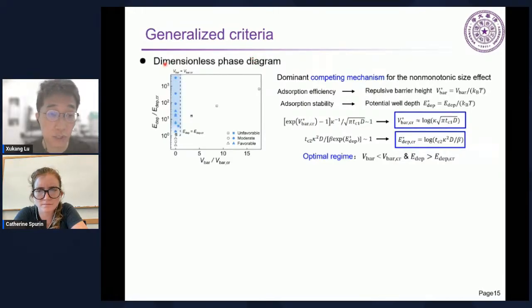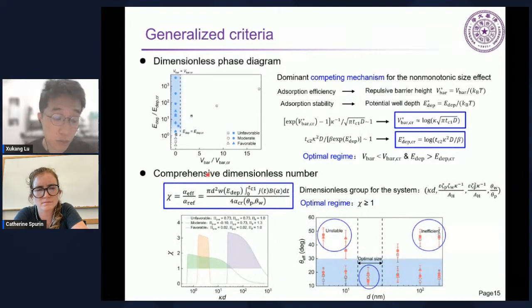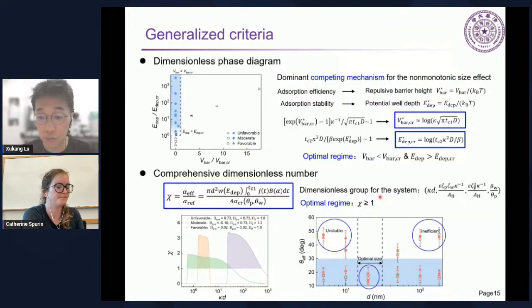So the first step is to extract this dimensionless phase diagram describing the dominant competing mechanism for the non-monotonic size effect. As we have explained before, it's a competition between the efficiency and the stability determined by the repulsive barrier and the potential well, and the predicted optimal regime fits well with all different experimental data. And in the second step, we formulate a comprehensive dimensionless number, and when it is larger than 1, we can directly determine the optimal regime, which means we can just tell people what the optimal size is. And even beyond size, as we show here, we have this dimensionless group description for the system.